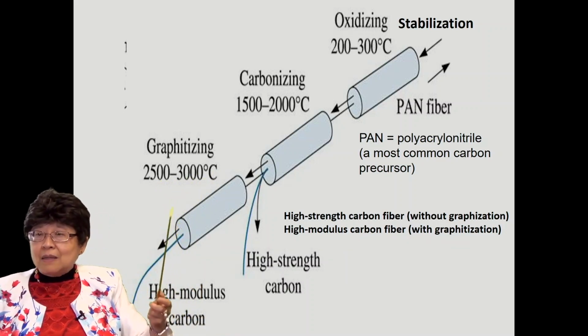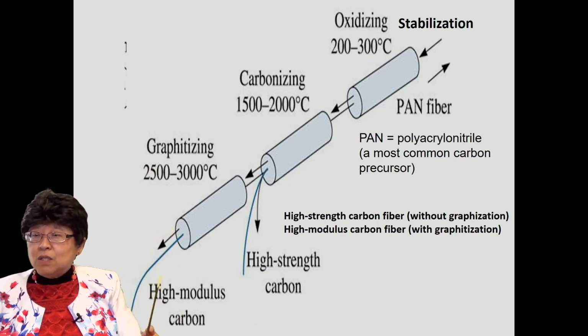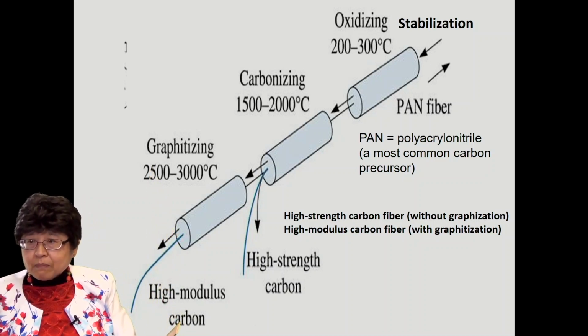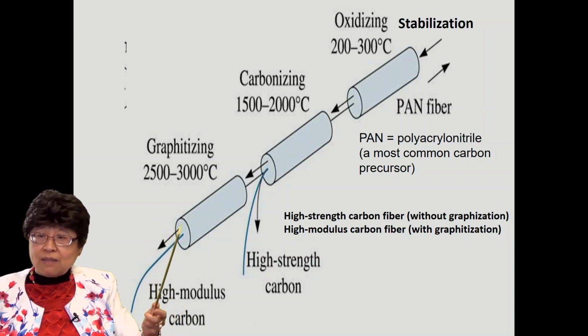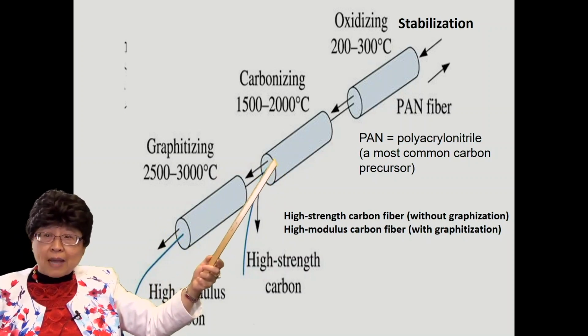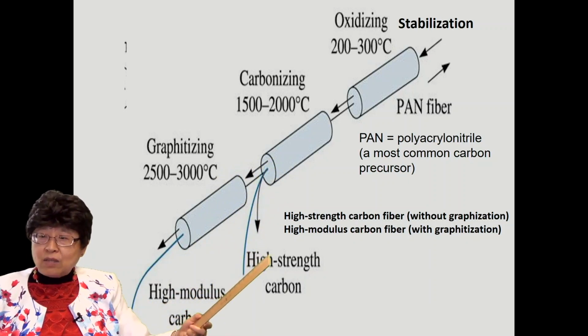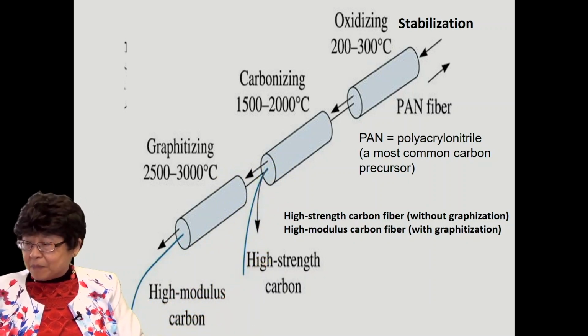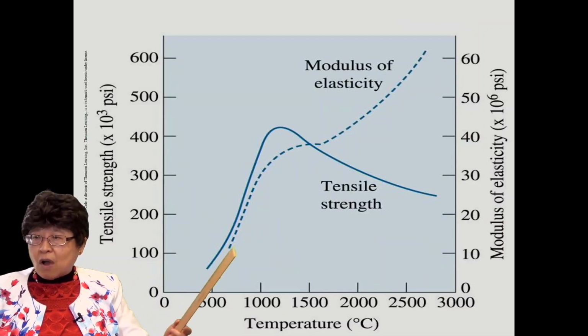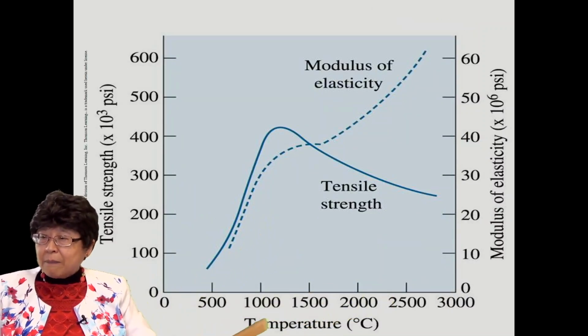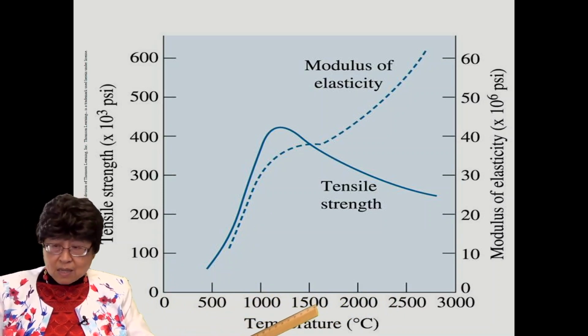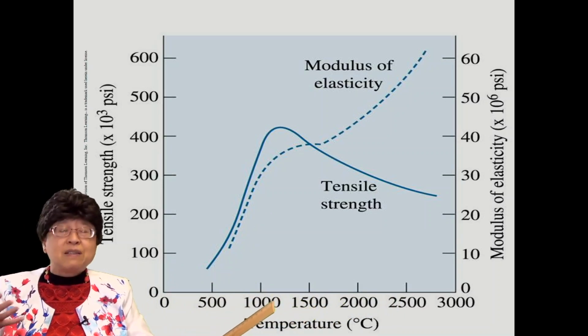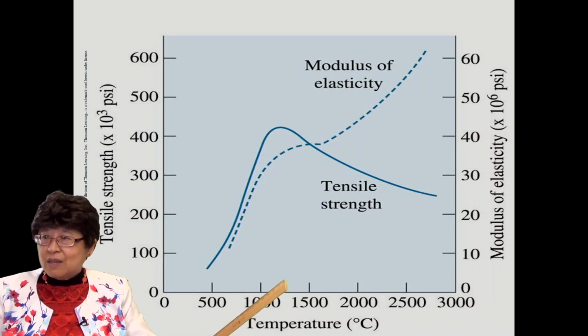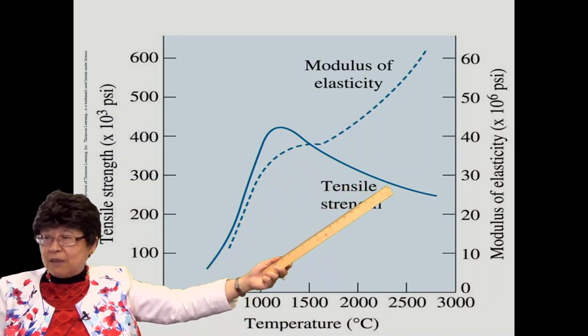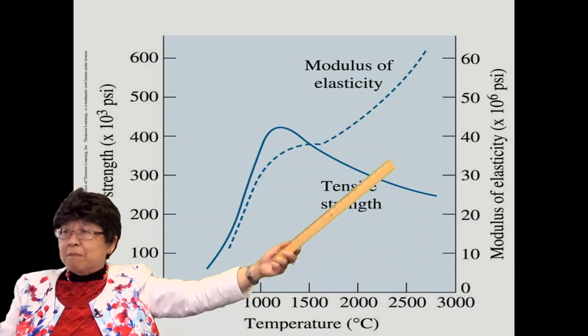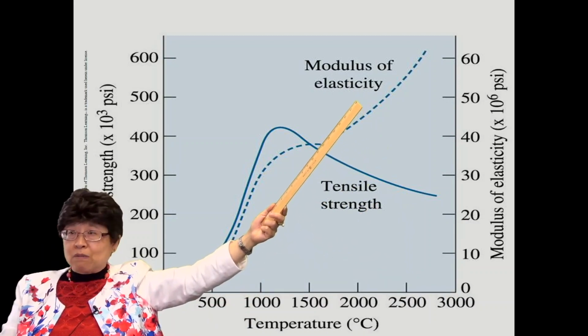Okay? If you do the graphitization process, you would end up with high modulus carbon fiber. But if you skip the graphitization process and stop at the end of the carbonization process, then you would end up with high strength carbon. Okay? So there are various grades of carbon fiber depending on the temperature that you use to fabricate the carbon fiber. We call that heat treatment temperature. That's the fabrication temperature. Okay? And the tensile strength drops if it becomes more and more graphitic. But the modulus keeps going up as it becomes more and more graphitic.